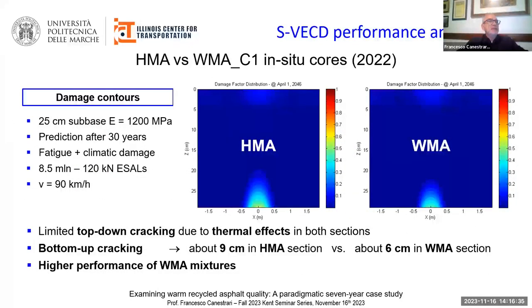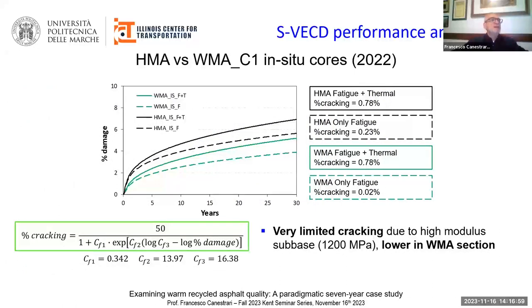Then, based on the damage contours obtained after the FlexPAVE analysis, we can see a limited top-down cracking due to thermal effects in both sections, whereas the bottom-up cracking is higher in the HMA section, meaning that the warm mixtures have better performance than the hot ones. Also, in terms of predicted pavement cracking, the results in this slide show very limited damage due to the high modulus subbase. However, in any case, the damage is lower in the warm section, independently if we consider only the fatigue or also the thermal effect.